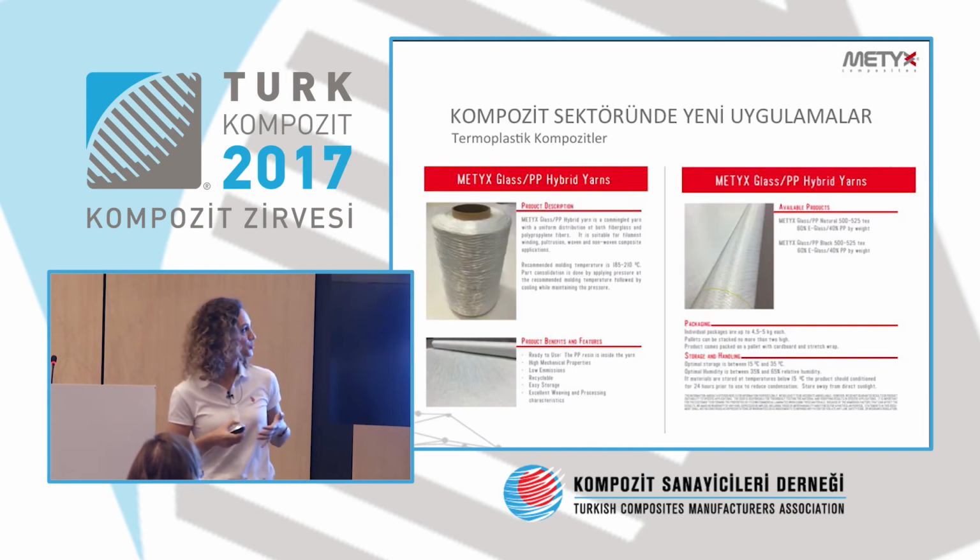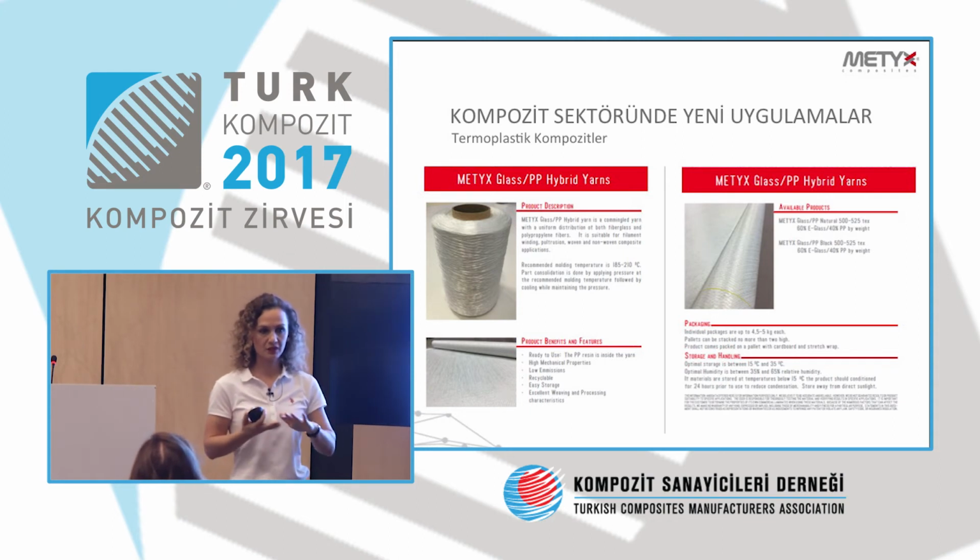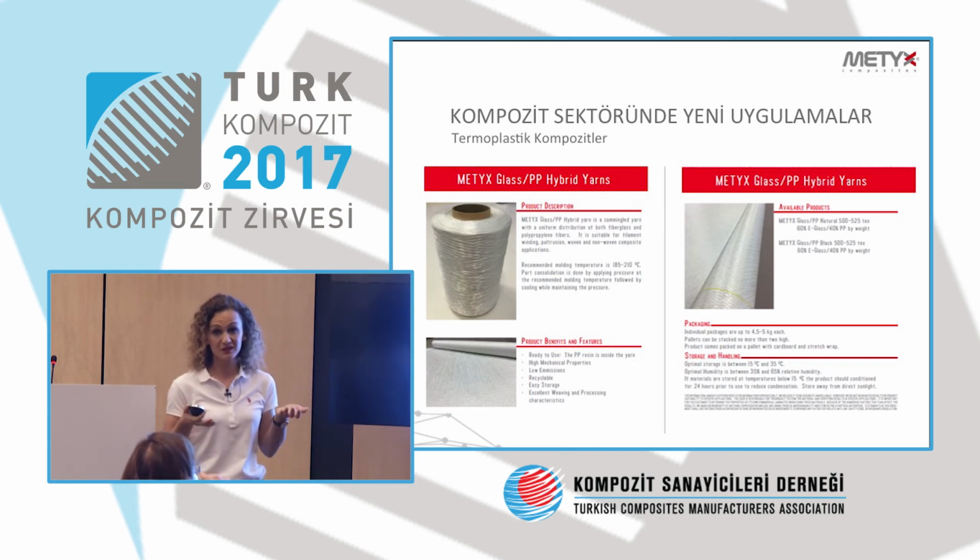As for here, we have developed a product. I can give you some information about it. It's a product you can see like a bobbin, and then it converts into a fabric. 60% glass fiber is involved, 40% is polypropylene. Later, at the melting temperature of polypropylene, you can press it and give the shape. Organosheets, the thermoplastic plates, are flat and rigid, so you can face certain problems putting them into the product itself. But here, with molding, you can give a shape manually.